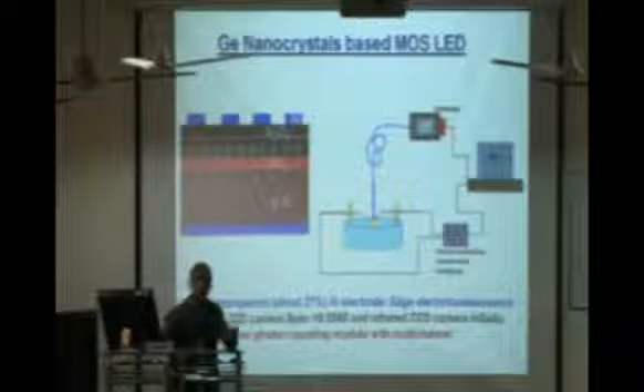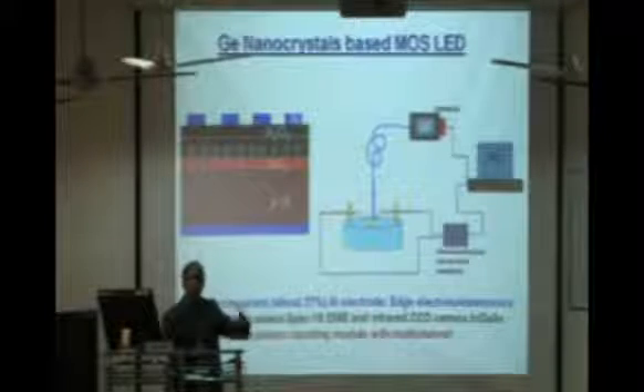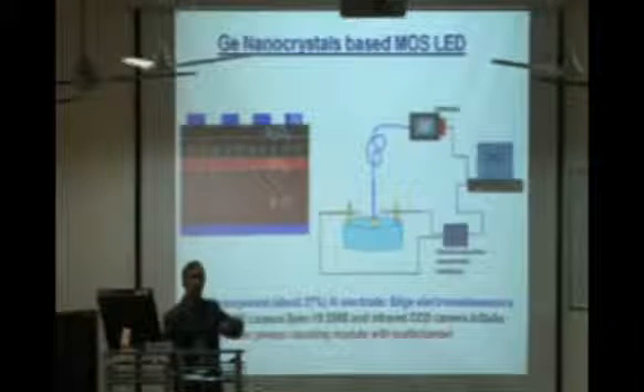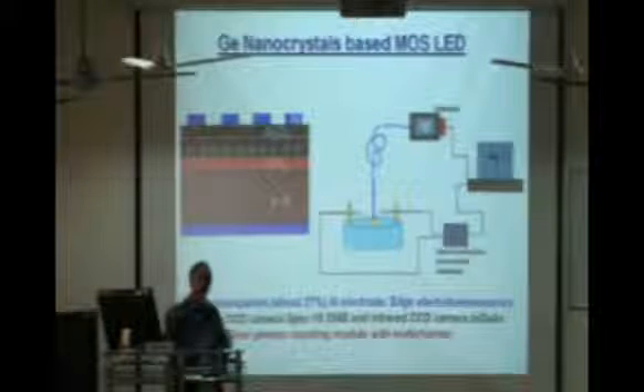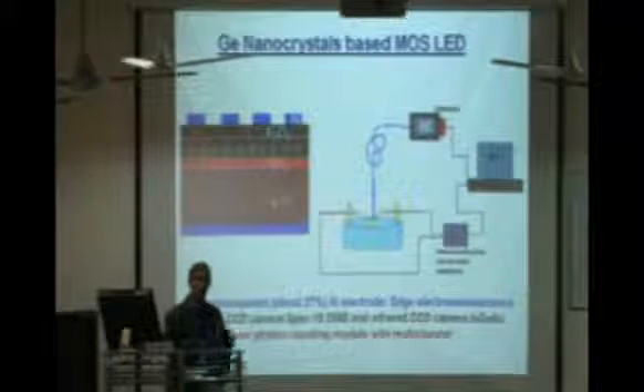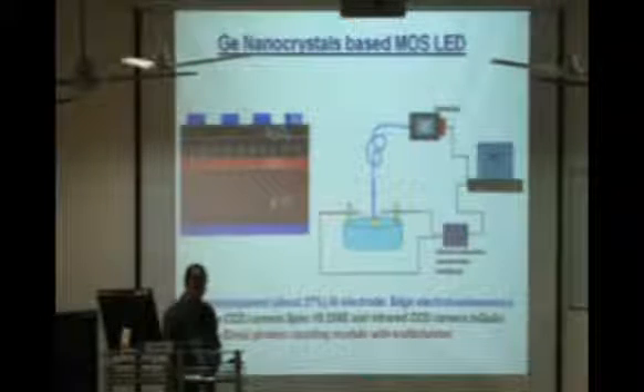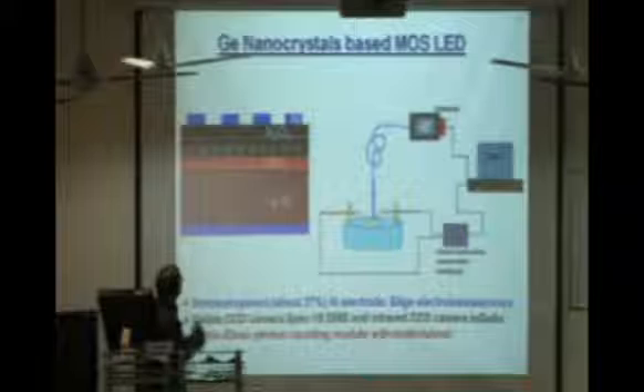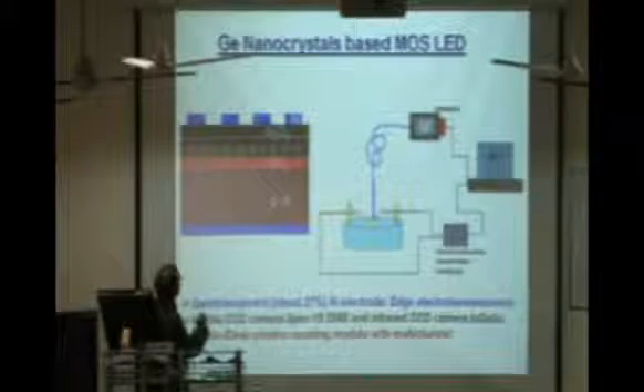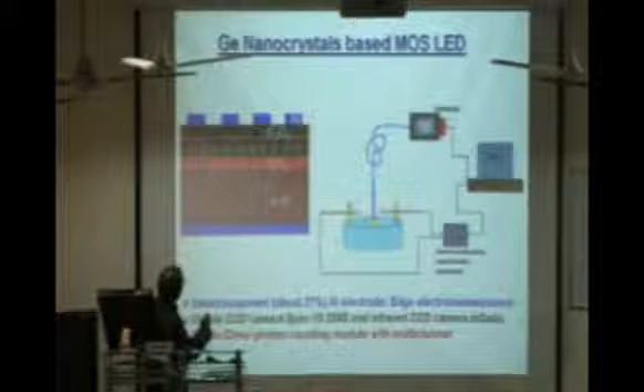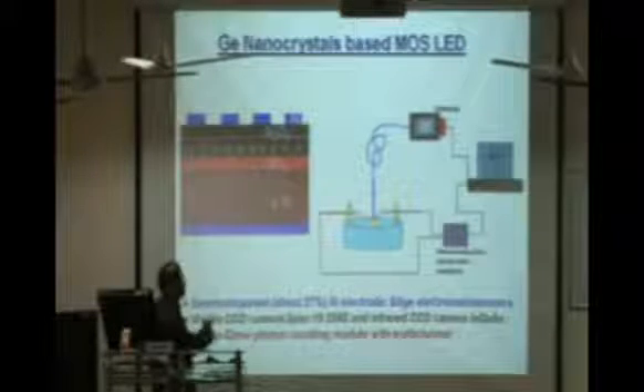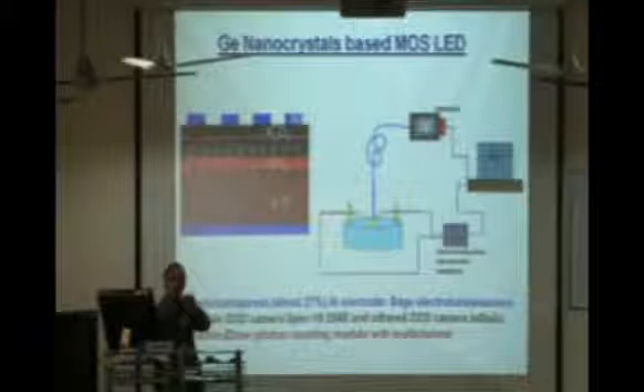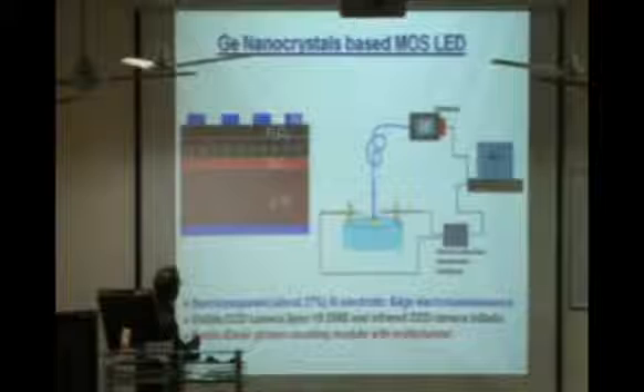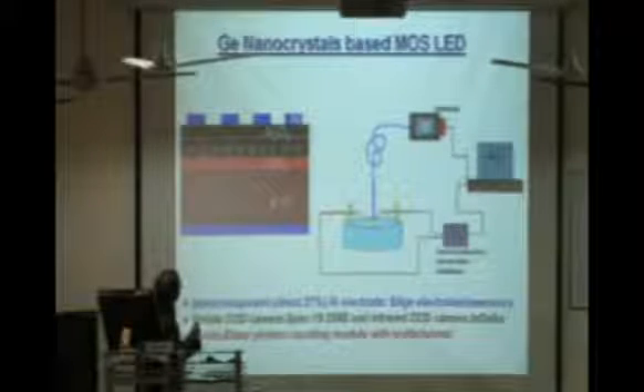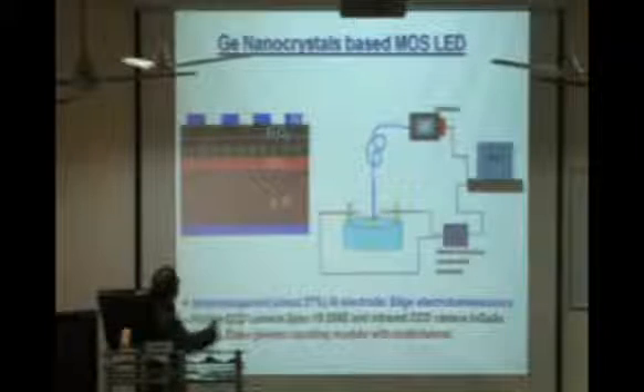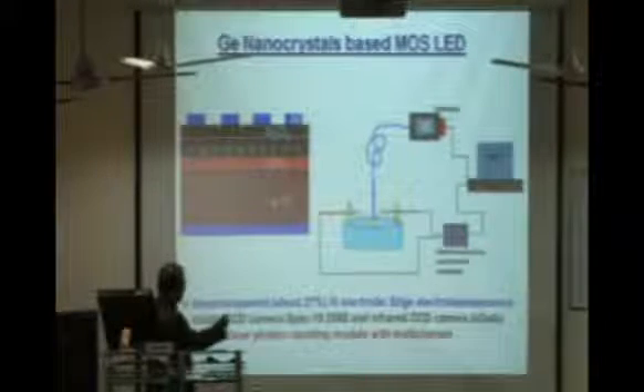Of course, for the device people, or the electronic engineer, you will not believe this photoluminescence. They say, can you give me some device, I will put a battery and the light will come on. That phenomenon is called electroluminescence. You apply the electric field, and if you get electron hole recombination, then the light comes on. So we have made a structure with these quantum dots in a different oxide matrix, like an aluminum oxide matrix in this case. And this silicon dioxide is a very thin layer which acts as a tunneling barrier, so that holes can be injected from this side and electrons can be injected into the quantum dots from this side. Then we try to detect this emission with a fiber optic coupled system.